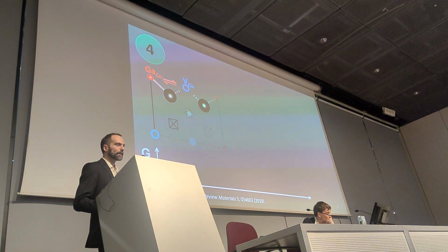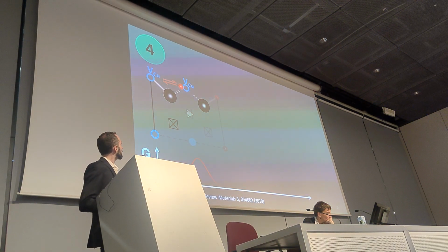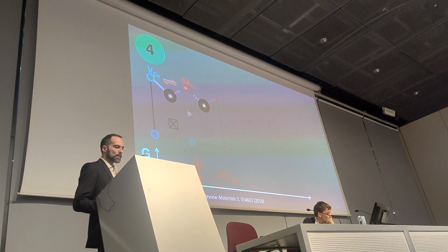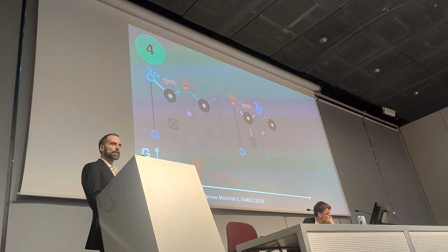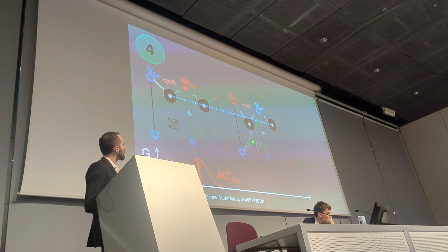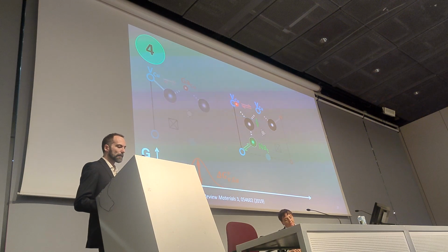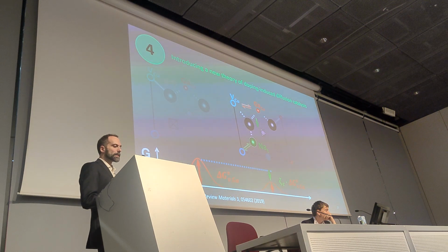And why? How? So whenever we have a diffusion of an atom from one location to another in a crystal structure, we have an associated energy barrier. So my proposal is that if we accept the idea that sodium can enter the lattice of CIGS as sodium on copper, but also in a tetrahedral site, we may acknowledge the possibility for the bonding environment of a selenium atom with a neighboring gallium that tends to try to migrate, to diffuse, to be altered. So if we alter the bonding environment, then we may have a lowering of the diffusion barrier. So effectively what I'm talking about here is that we are introducing a new theory of doping-induced diffusion catalysis in the solid state.